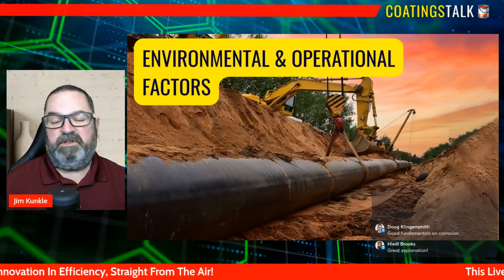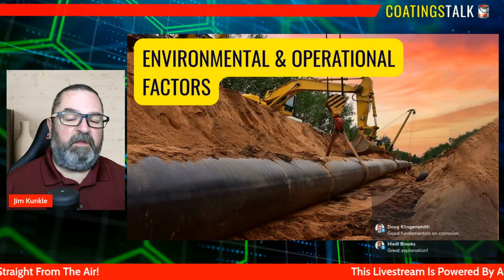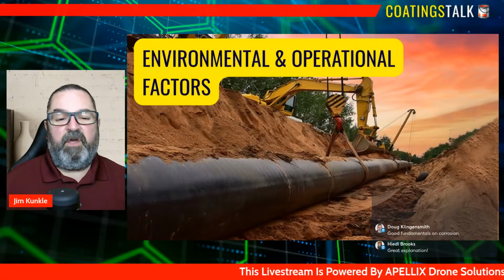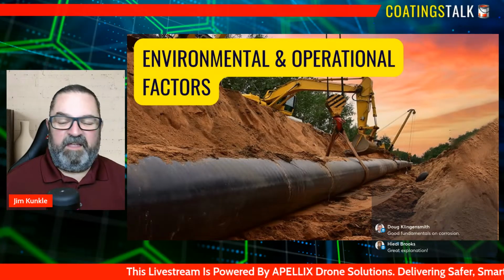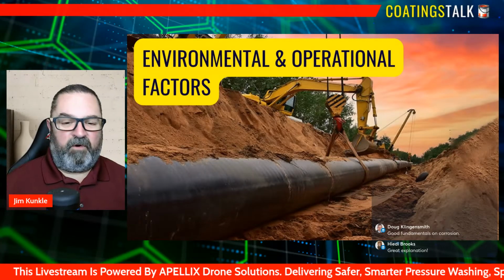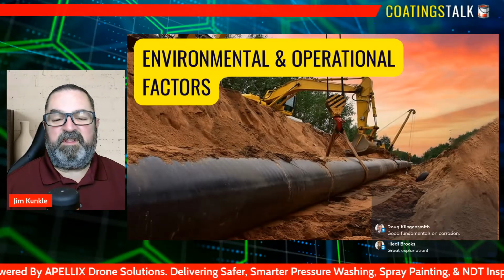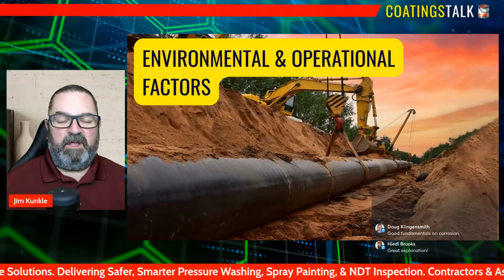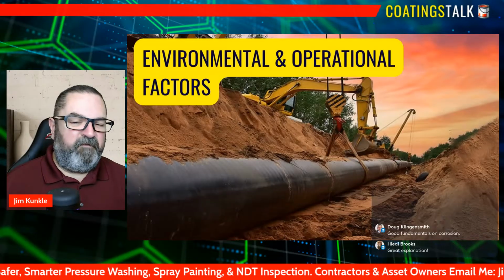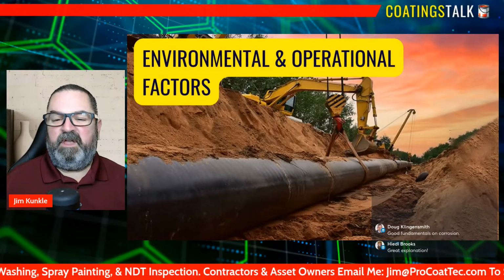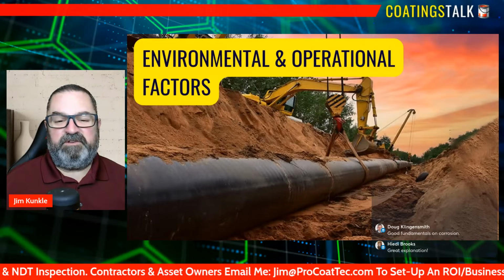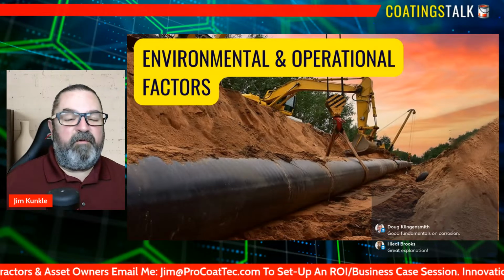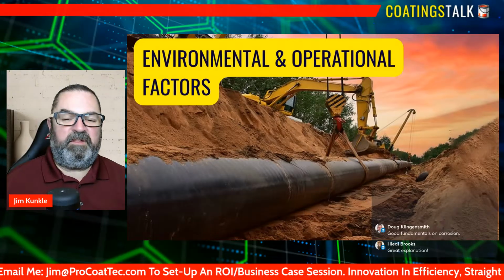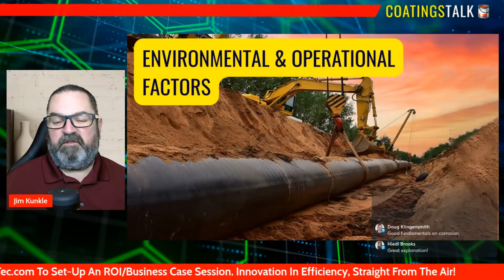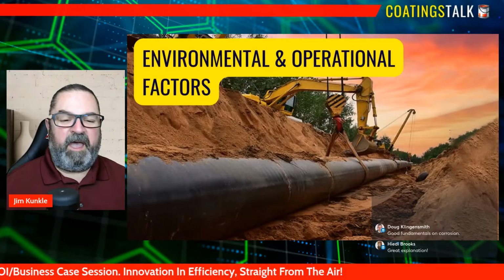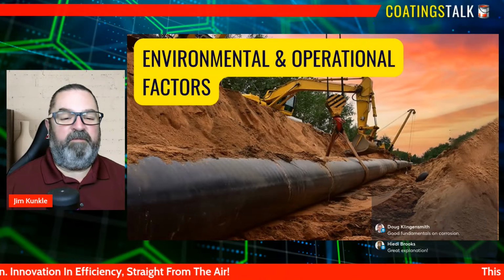When environmental conditions such as humidity or temperature are outside the recommended range during application, the coating may never achieve its intended performance, and this leaves the asset vulnerable long before its expected service life. Together, design flaws and poor application practices create the perfect storm for early corrosion. Field professionals who understand these risks can better identify vulnerable areas, adjust inspection priorities, and advocate for corrective actions before failures occur. And this awareness transforms corrosion control from a reactive task to a proactive strategy, protecting both the assets and the people who depend on them.